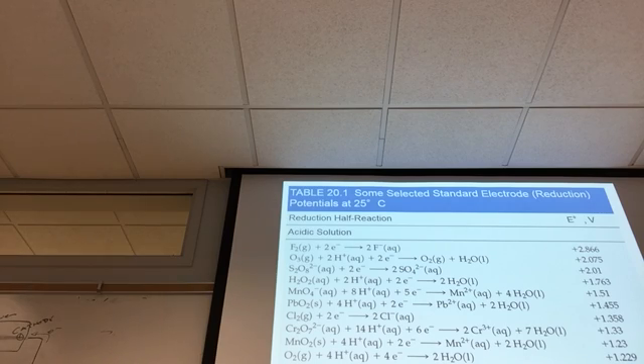For everything, you're going to oxidize the species with the highest oxidation potential, except for one exception. And this is it. The one exception is this. Chloride turns out to be oxidized even though it has a lower oxidation potential. And the reason that chloride is oxidized is because of kinetics. When you oxidize chloride, you just pull off an outer shell electron. It's not difficult. Pull off an outer shell electron.